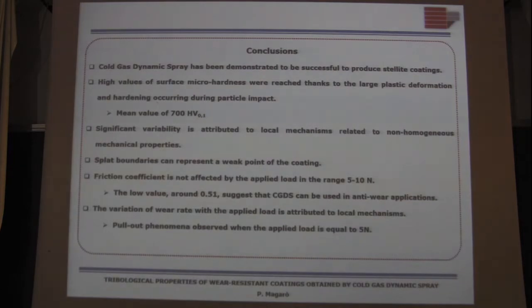On the other hand, the friction coefficient is not affected by the applied load in the range 5-10 Newton, and its low value around 0.5 suggests that cold gas dynamic spray can be used in anti-wear applications. And the variation of the wear rate with the applied load can be attributed to the local mechanism. In fact, the pull-out phenomena can be observed only in the test in which the load is equal to 5 Newton.